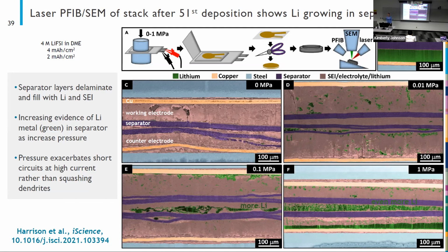Okay, yes. So the first part of the question, everything that we've looked at is uniaxial stress. So this is not hydrostatic stress. It's unclear what exactly would happen in the battery, but it is probably more likely to be uniaxial stress, I would guess, unless there's gas that's forming to compress everything more evenly. So we haven't done a hydrostatic stress comparison. I have seen some modeling on that, I believe, but everything we've done is uniaxial and not hydrostatic.